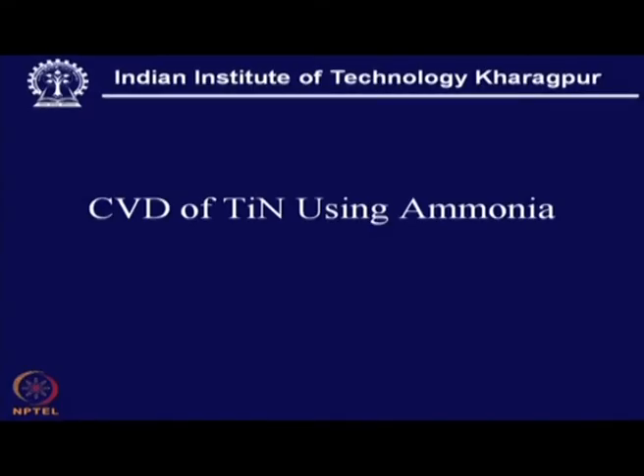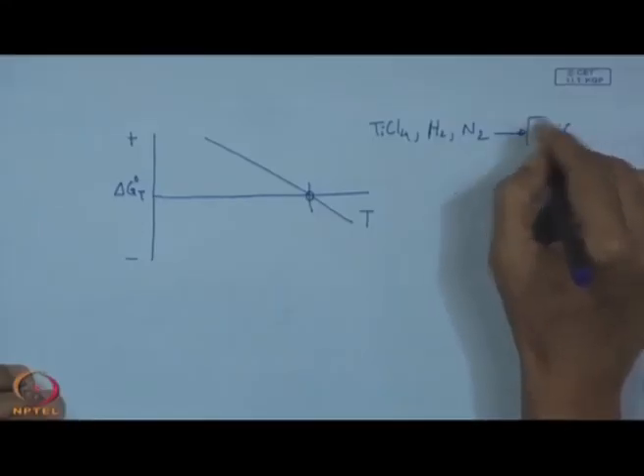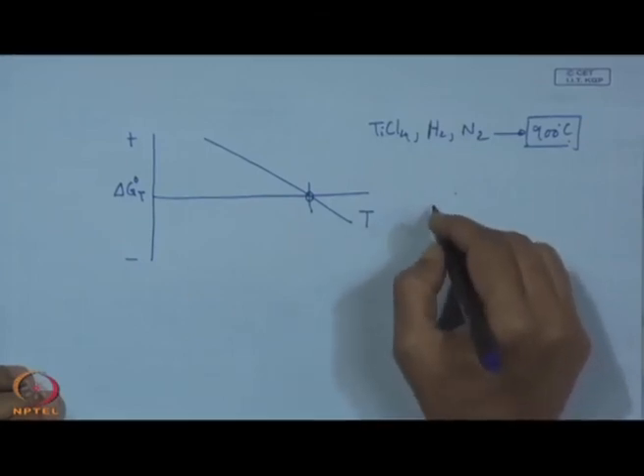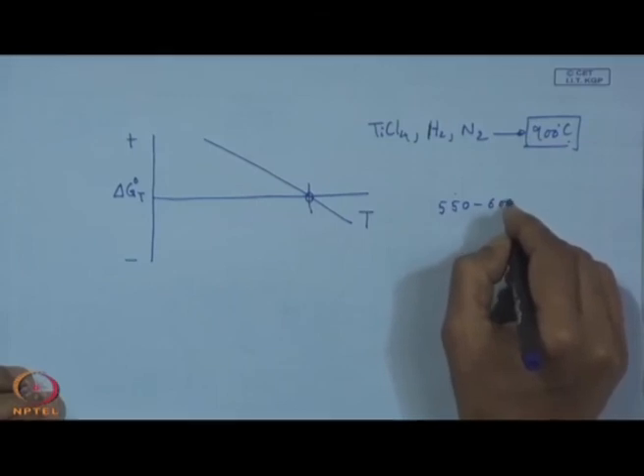So, it is actually CVD of titanium nitride using ammonia, and what we have seen at the very beginning, that if it is the delta G0 versus T, so this is the temperature. When it is the reaction using TiCl4, hydrogen and nitrogen, then we have a temperature here which is around 900 degrees centigrade for this reaction to occur. But if one is interested in having a low temperature CVD, so this is in the order of at least 900 degrees centigrade, but if one is interested in the CVD around 550 to 600,